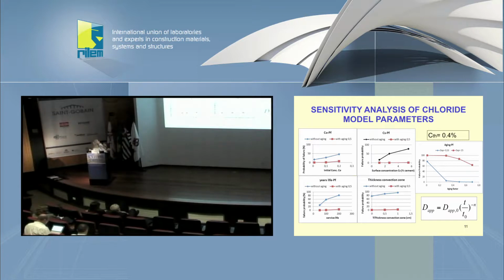Here I present the sensitivity analysis of the effects of the different parameters in the model, assuming a chloride threshold of 0.4, but if the initial concentration is higher, really we are decreasing the chloride threshold. In that case, without aging in blue or black, and with an aging factor of 0.5. And this is one thing.